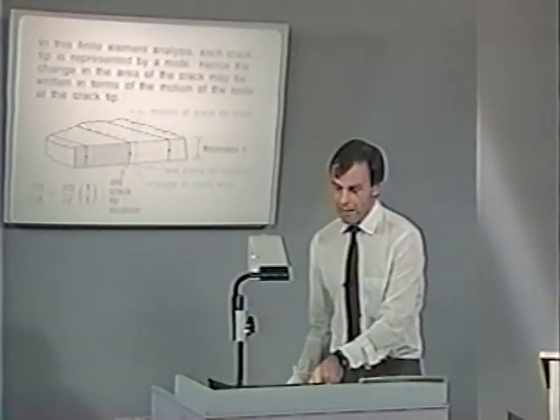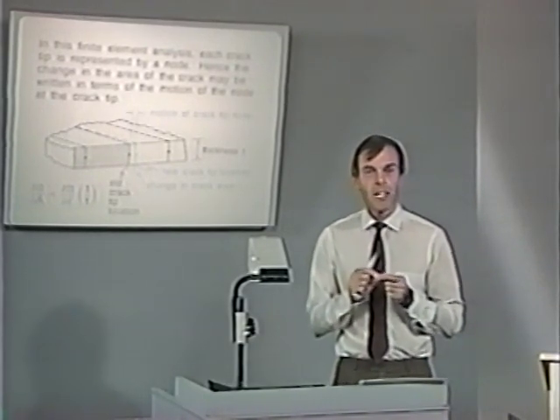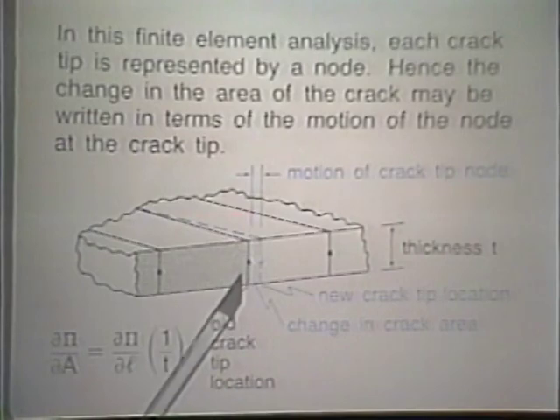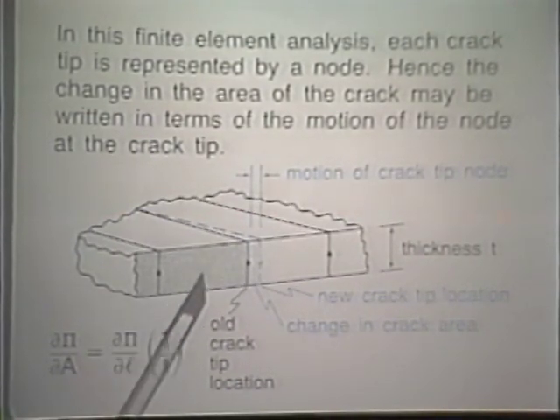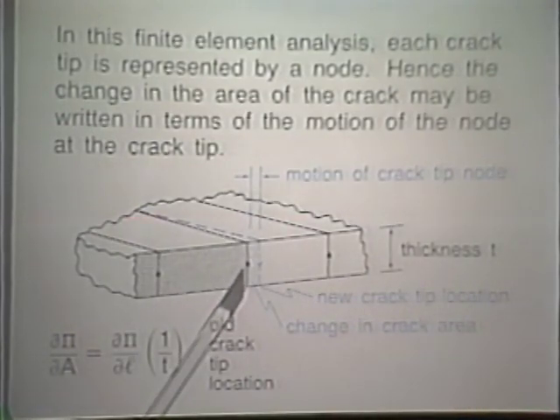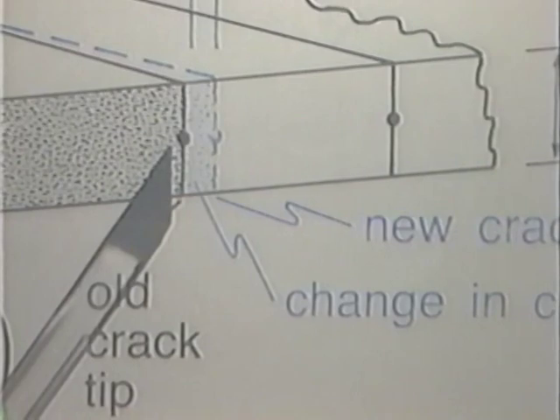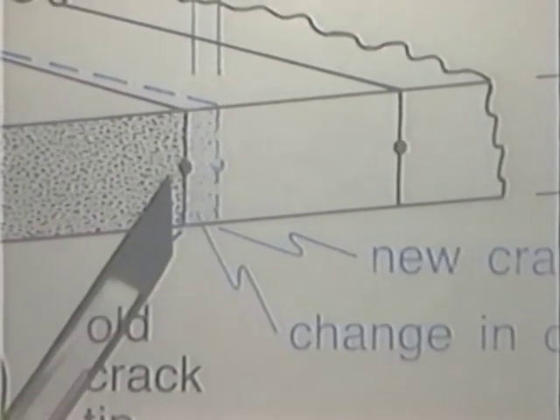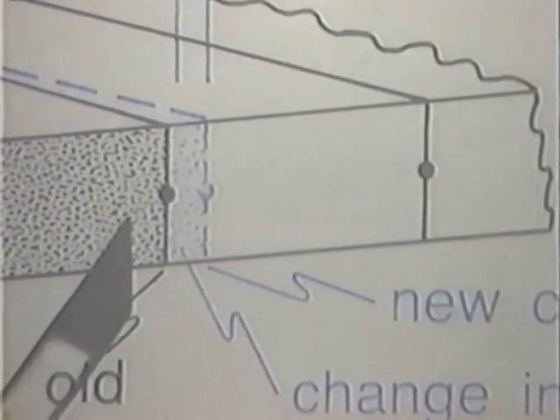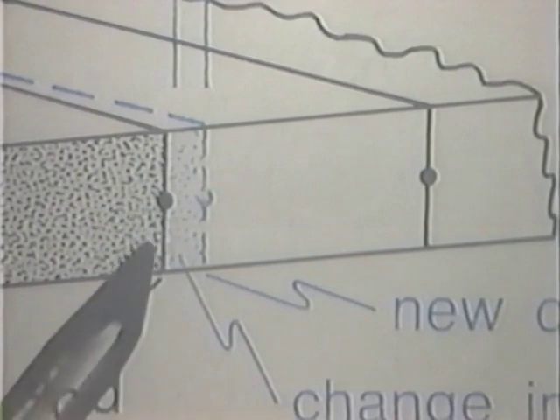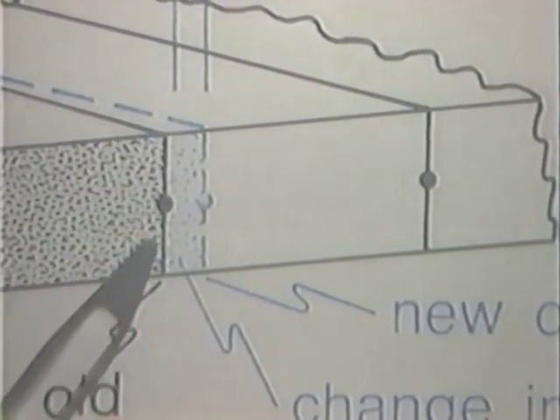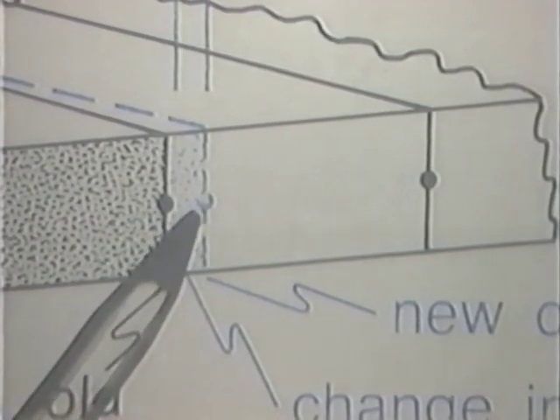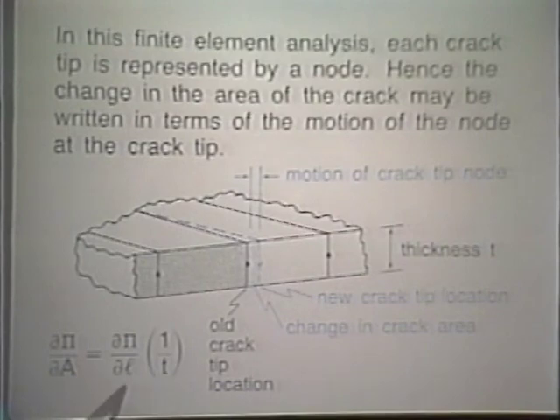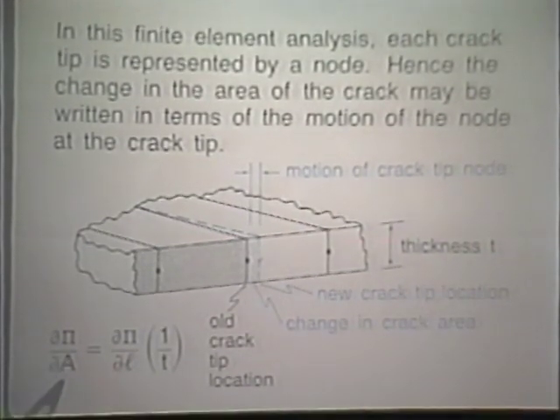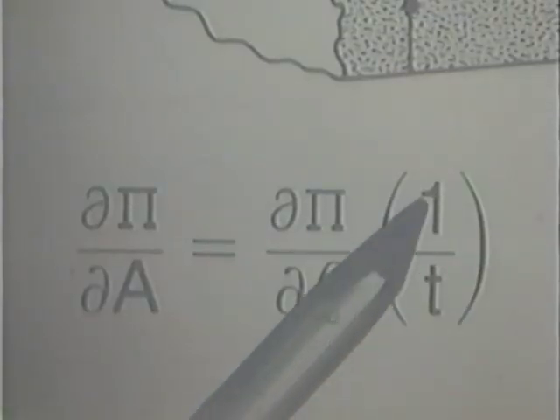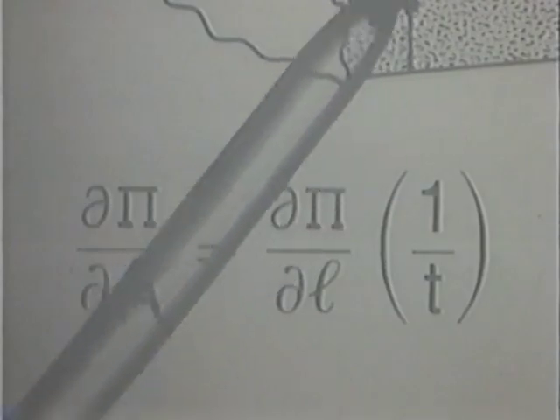Well, in this finite element analysis, each crack is really represented by a node. If we look at a cut through the plate, where this here is the crack, we have this here as the node at the crack tip. This node in the finite element analysis is, so to say, moved forward a differential amount so that the change in crack area is given via this little bit here. Note that the original crack tip location is here, and the new crack tip location is right there. Then we can, in this process, evaluate del pi over del A as del pi over del L times 1 over t, where t is the thickness of the plate.